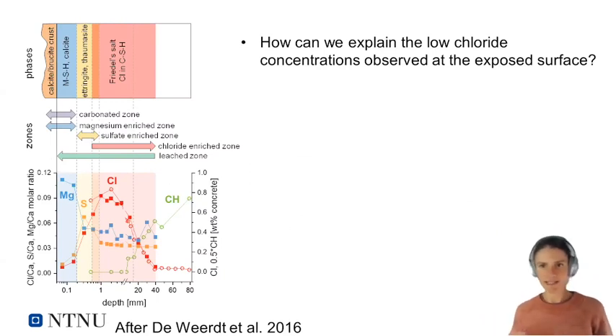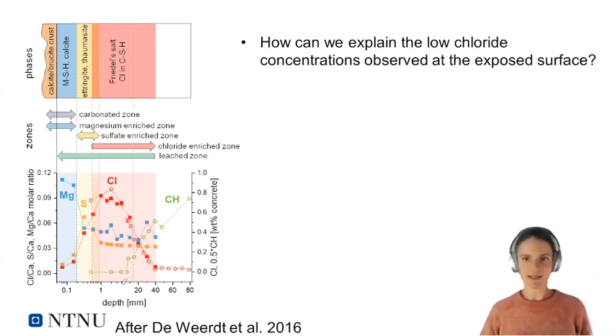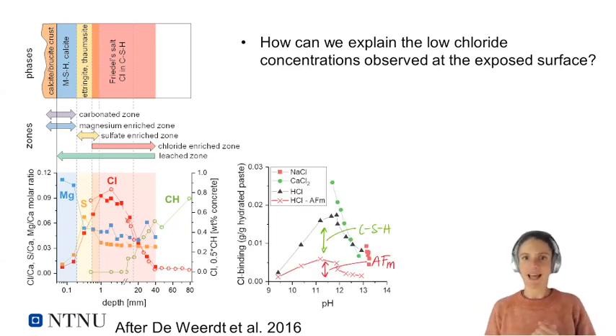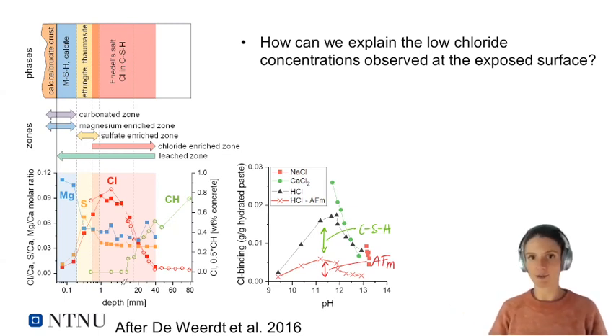Now we've seen that chloride binding is pH dependent. So how does that relate to our research question? We were wondering, how can we explain these low chloride concentrations at the exposed surface? I first need to say, a large part of the chlorides in the chloride profile are bound, so chloride binding will explain this. Let's combine the figure with pH-dependent chloride binding with the chloride profile we've been looking at earlier, showing this very low chloride concentration at the surface.